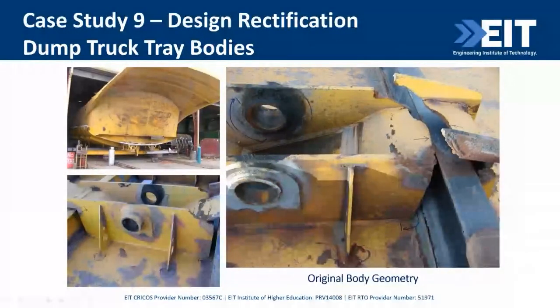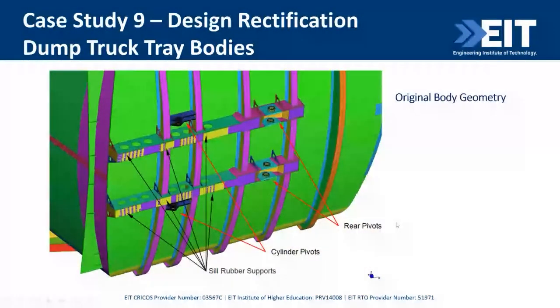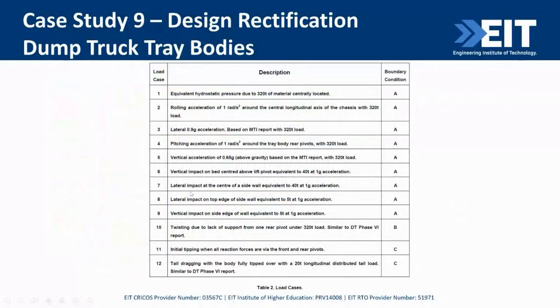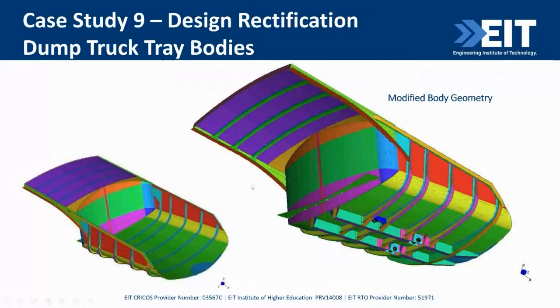And unfortunately, the cracking there was horrific. So, I mean, you've got operations with shovels. The shovel operations weren't flash. The haul roads from the fill to the dump weren't good. So, you've got impacts from loading and uneven loading. You've got higher than should be accelerations, and you've got an unfortunately weak design, and that's the result. So that was all gone through with looking at the load cases. Again, load cases. So 12 load cases set up, including your tail dragging of your dump, the loading, etc., your lateral accelerations, rolling and lateral. And that was all set up and properly sorted out through your FE.